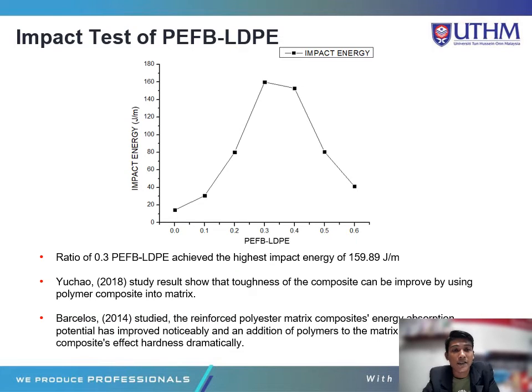For the impact test of PEFB LDPE, ratio 0.3 achieved the highest impact energy of 159.89. The Yuchao 2018 study results show the toughness of the composite can be improved by adding the polymer composite into the matrix. In the Barcelos 2014 study, the energy absorption potential of the reinforced polyester matrix composite improved noticeably, and the addition of polymer to the matrix increased the composite hardness dramatically.